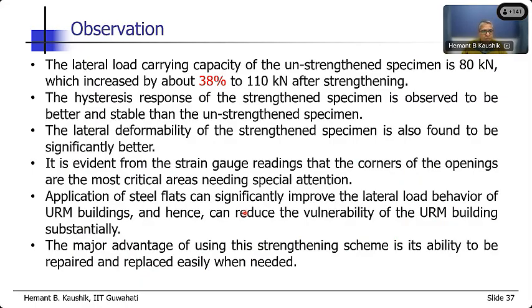These are some of the major observations which I have already discussed, that the load carrying capacity of the strengthened building increased by about 38%, which is good. 38% increase in strength is good, but more importantly, the lateral deformability of the strengthened building improved significantly by almost 50%. That is what we were looking for. How do we delay the failure? How do we delay the brittle failure in these buildings? Of course, the final failure will be brittle, but then the delay is very important for such brittle structures. Then the hysteretic response was more stable and it was better for the strengthened building that we have already seen.